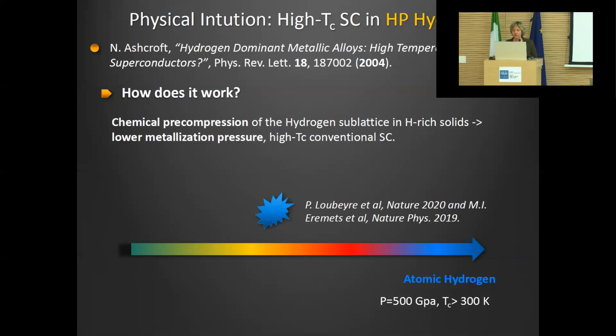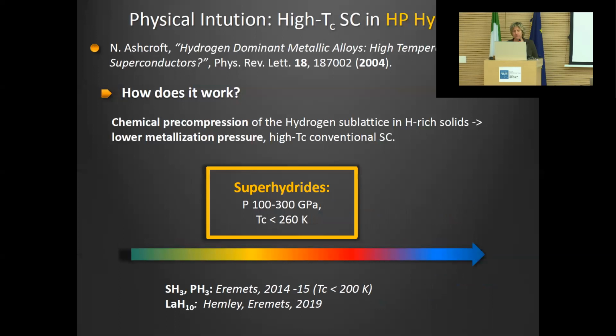And for a long time, this was considered equally impossible. And there are actually a couple of reports from this year which show that we may be almost there. But anyway, in 2004, when Ashcroft wrote this important paper, 500 GPa was out of the question. But what it was possible to achieve was pressures in the order of 100 to 200 GPa. And Ashcroft's idea was that if one can achieve pressures of 100 or 200 GPa, this may be enough.